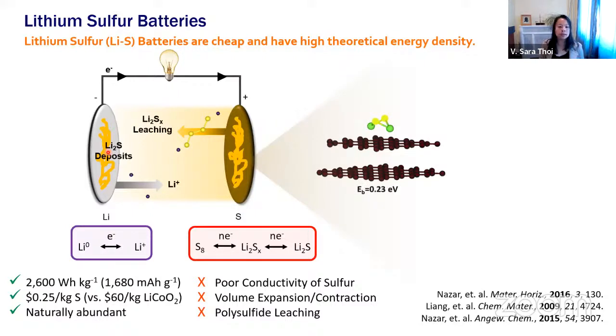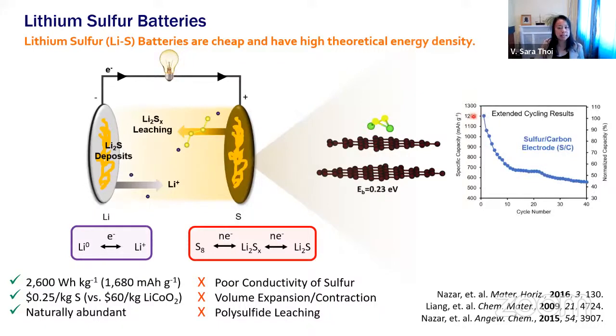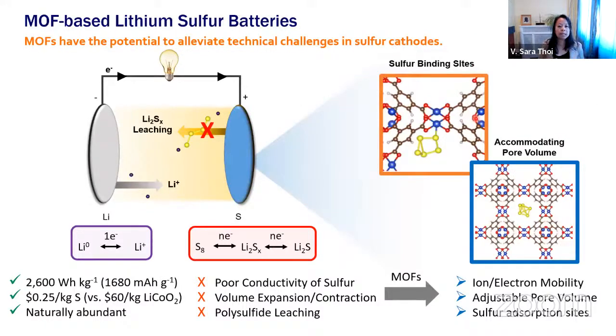Current materials that are used in lithium sulfur batteries have primarily been carbon-based, and that's really due to the excellent physisorption properties of carbon. But you'll see here that despite the very high initial capacity that we get in the beginning, at about 40 cycles of charging and discharging your phone, our capacities are much, much lower, about 45% of the initial specific capacity. So when we started, we thought, well, maybe we could use some of these really nice, well-controlled molecular materials like metal organic frameworks to understand this process. In particular, metal organic frameworks have binding sites that allow for the encapsulation of polysulfides within their pores. The organic nature of metal organic frameworks allows for flexibility to accommodate pore volume changes. And of course, by adding functional groups, we may be able to encourage charge mobility.